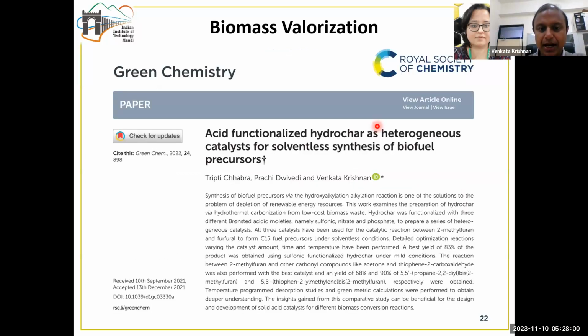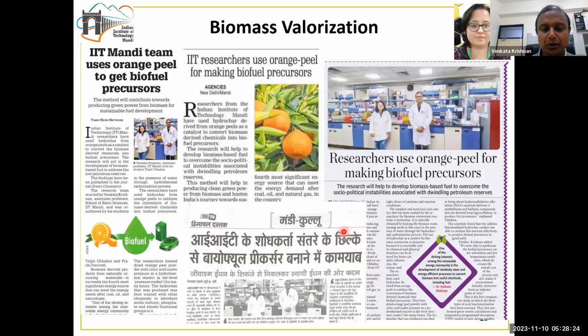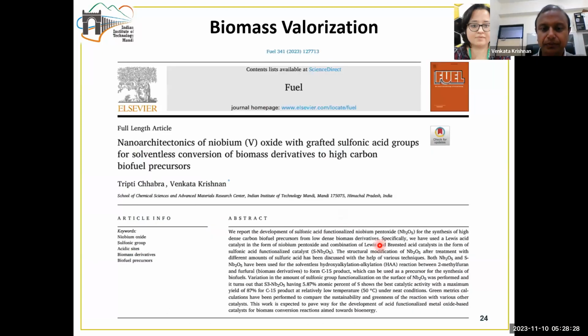In yet another work, we have taken hydrochar from waste orange peels, and then we functionalized the hydrochar using sulfonic, nitrate, and phosphate groups, and then used it for this HAA reaction, which leads to the formation of C15 fuel precursors under solvent-free conditions. These are biofuel precursors, and we eventually were able to get these biofuel precursors prepared using this catalyst. And this work was also highlighted by several news media during that time.